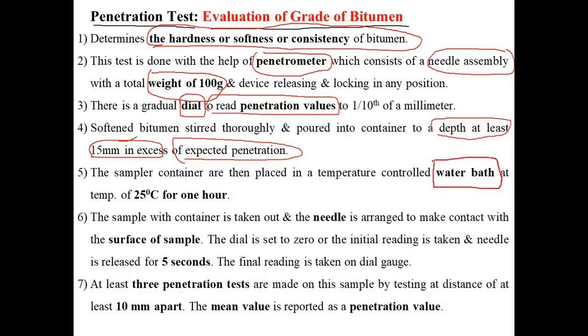A water bath is one more device where we take water, and there is also an arrangement to maintain a particular temperature of that water. Inside that water you have to put the cup, and the temperature maintained is 25 degrees Celsius for 1 hour. So it will cool down the bitumen taken into the cup. After that, take the cup out and keep it for the penetration.